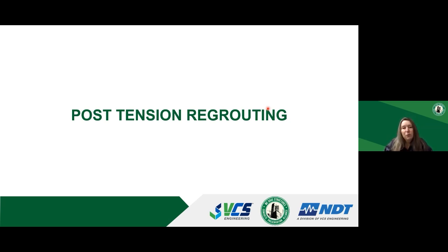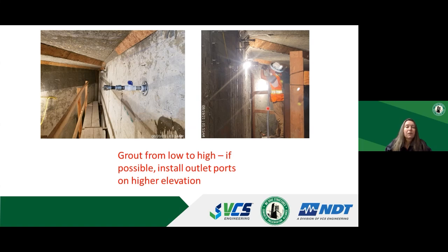When there are large voids present along the tendon, the tendons can be regrouted. Grouting can be done using the positive pressure approach. This is what you see on the slide, where grout is pushed in from the low point and the technician watches for the grout to come out at the high point of the tendon drape. Grouting can also be done using vacuum assisted grouting.